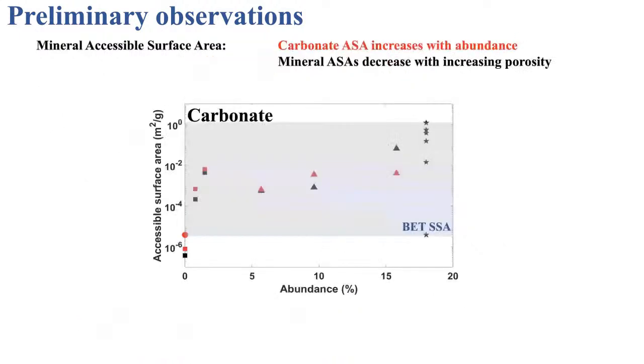In terms of accessible surface area, we see that carbonate accessible surface area increases with abundance. And just for comparison here, these are the BET specific surface areas that we've collected from the literature shown as stars. And we've just highlighted this region to give you an idea of how these accessible surface area values compare with the BET specific surface area values.